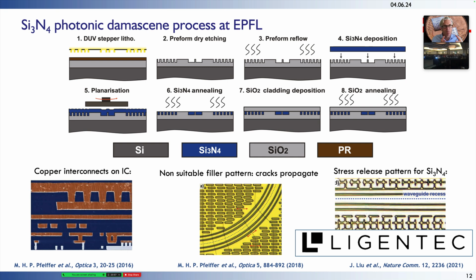But as I mentioned, the Damascene process is only one part of the low loss. The other part is really the crack mitigation. So every one of these chips, also if you look at commercial chips from Ligentec, you see these checkerboard patterns. You always need to make sure that you avoid crack formation of the LPCVD nitride on the wafers itself.